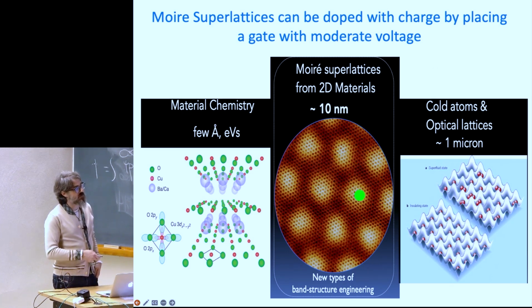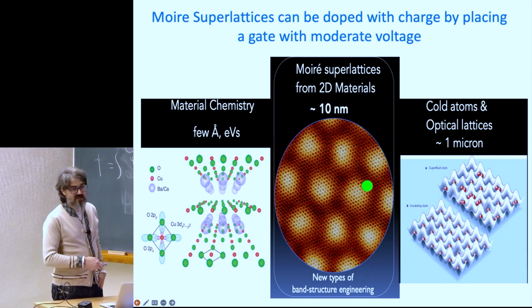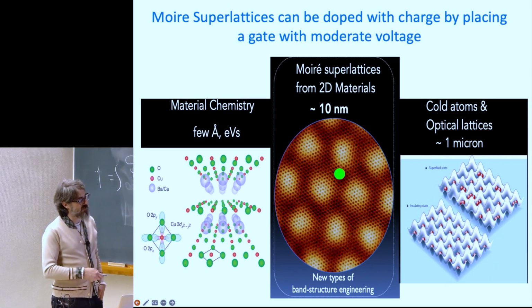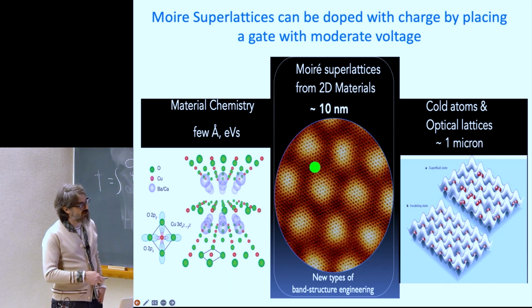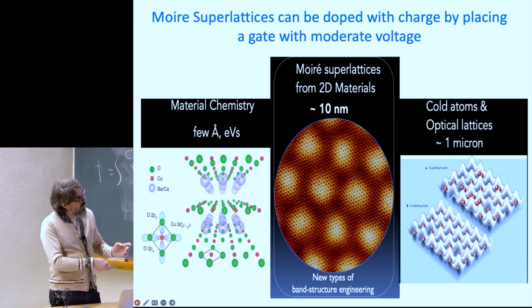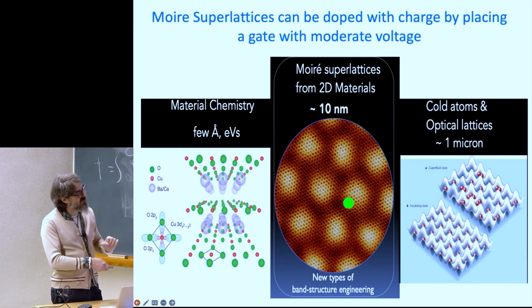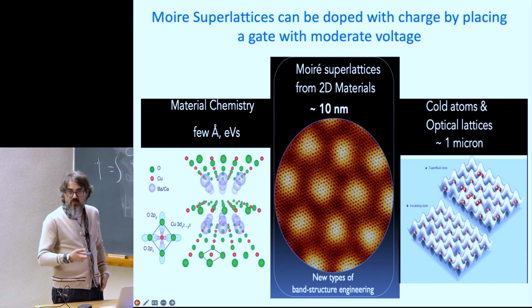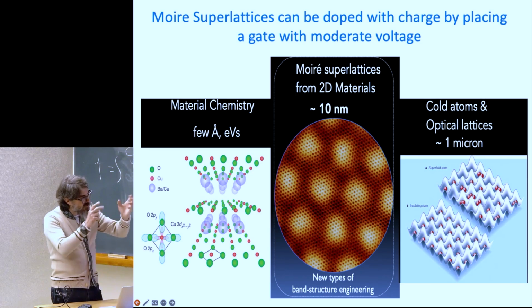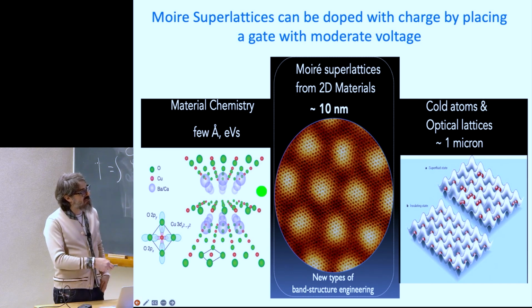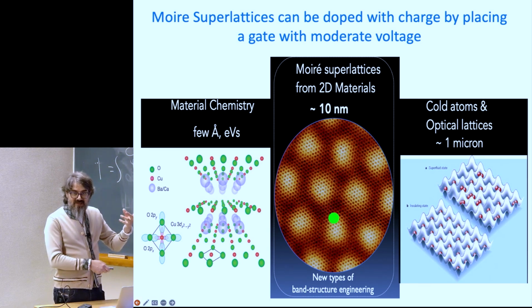And you can clearly see here the graphene lattice, but you can see a superstructure that has appeared on top of it. This superstructure shows basically what you would see if I didn't show you these smaller initial lattices, right? The small hexagons are just the graphene carbon hexagons. These are the superlattices. You'd say that these are new orbitals or new degrees of freedom, right? If I just showed you a picture without showing you the smaller lattice. But these degrees of freedom really are made of thousands.